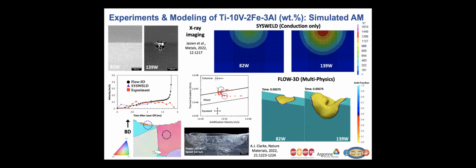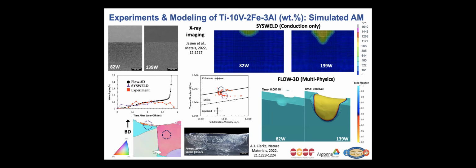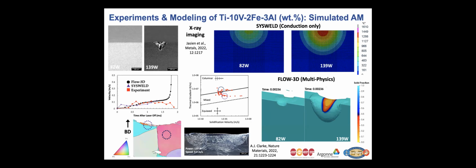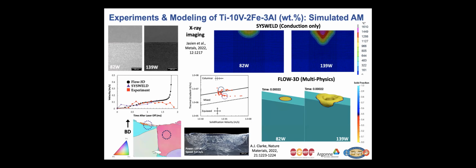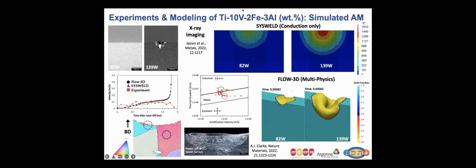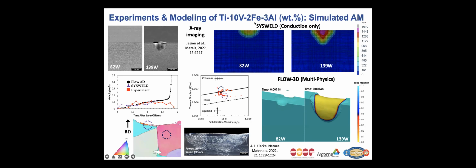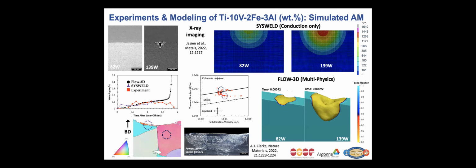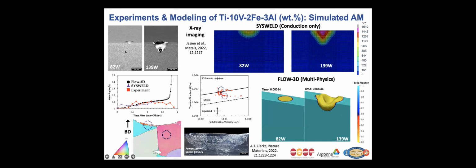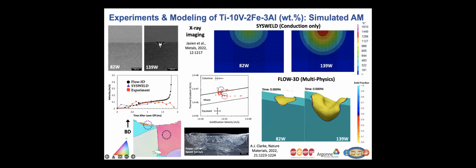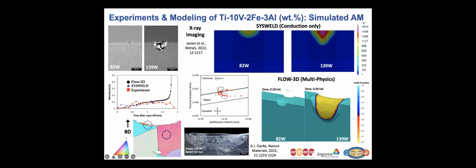So one of the bummers about Ti-6-4 is that we actually have the solid state phase transformation to deal with. So more cleanly to look at solidification, we've been looking at metastable beta Ti. This is Ti-1023. Basically that high temperature beta Ti phase we can retain at room temperature. So here are some synchrotron X-ray spot melts that we have from some of our Ti-1023 experiments. Here we're directly comparing that to our modeling again.